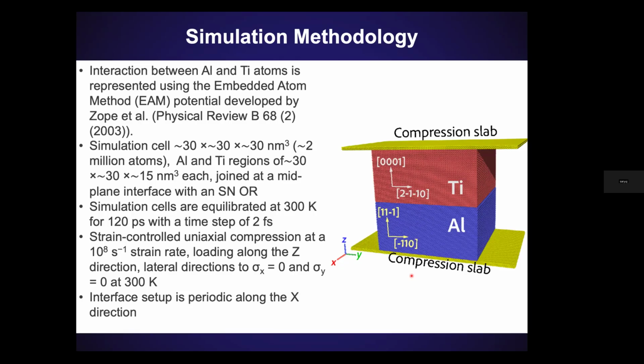All the simulations were done at room temperature. Another thing to keep in mind is that the strain rates in the simulations that we're running are really high. They're 10 to the 8 per second. And also, before we did the shock simulations, we actually wanted to just look at compression testing between the two materials as a function of that interface shape, because that gives us an idea about how the dynamic response would change. So that's what we're going to start with.